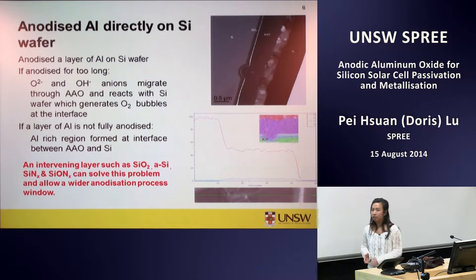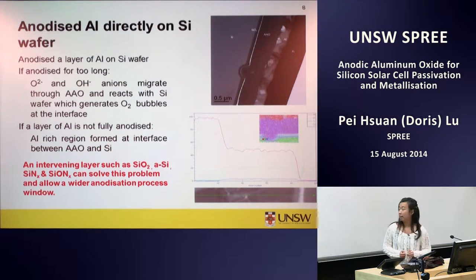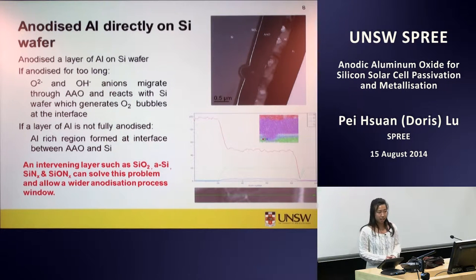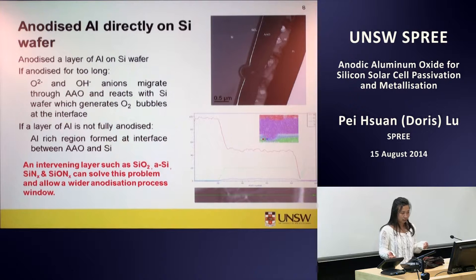So at the beginning, we tried to directly anodize a layer of aluminium on silicon wafer to replace PECVD aluminium oxide or silicon dioxide as a passivation layer. However, when the aluminium is fully anodized, the process doesn't stop at the silicon layer, the current will suddenly shoot up. The silicon underneath will start getting anodized. And during anodization of silicon to form anodic silicon dioxide, oxygen bubbles will form and create a gap between the anodic aluminium oxide and silicon wafer. This results in poor passivation compared to thermal silicon dioxide.